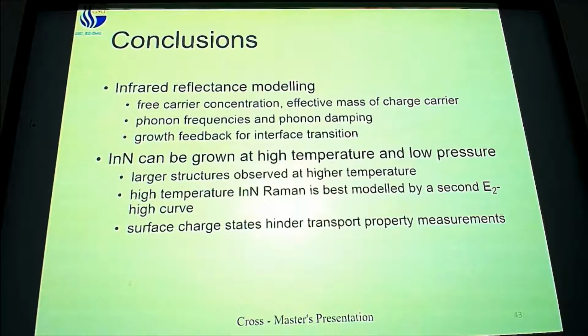And there is a distinct possibility that surface charge is affecting the transport measurements for this entire series of runs because these samples are so thin. Sitting at 50 nanometers, we might not be getting a true measure of the sample's properties itself.